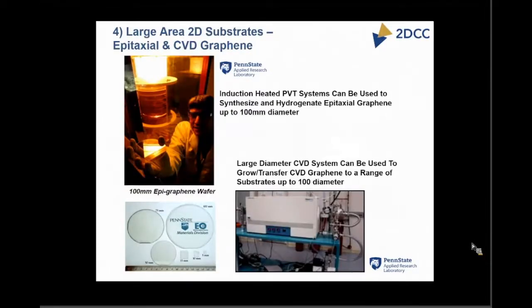Another quick point: although graphene is not directly part of the MIP, we have here at Penn State the capability of doing large area sublimation growth of graphene, and a lot of work was done by Josh Robinson early in this program to develop processes to synthesize hydrogenated epitaxial graphene and CVD graphene up to 100 millimeter diameter samples. If these are of interest, by combining them with other material systems, this capability is available.